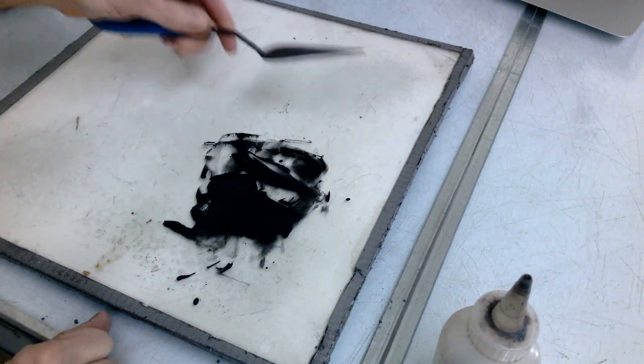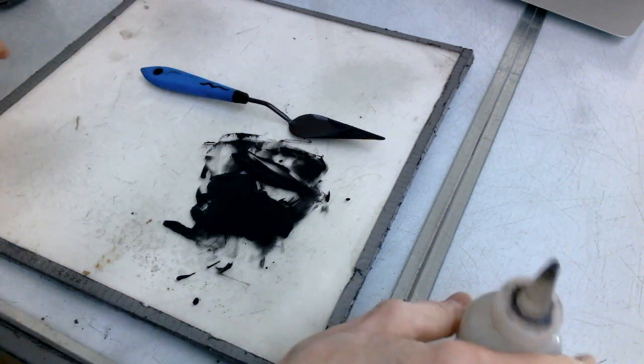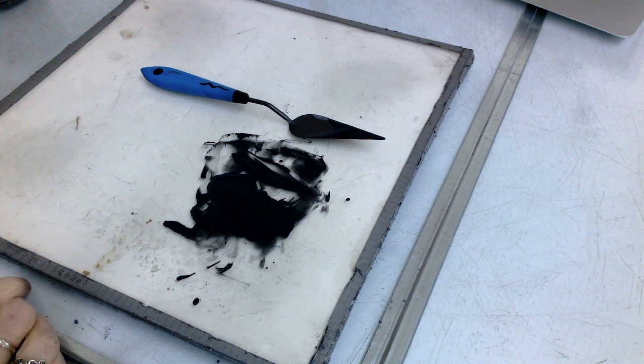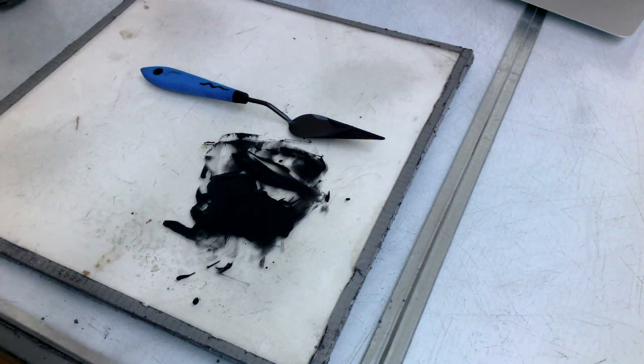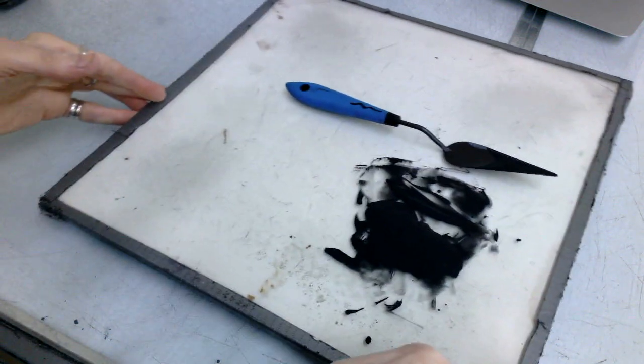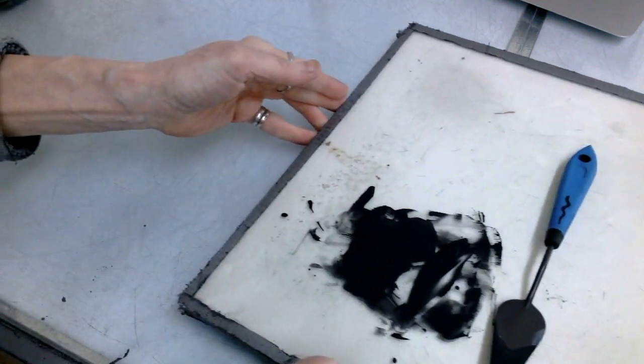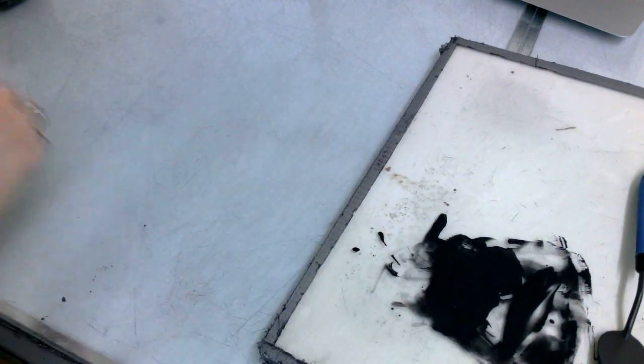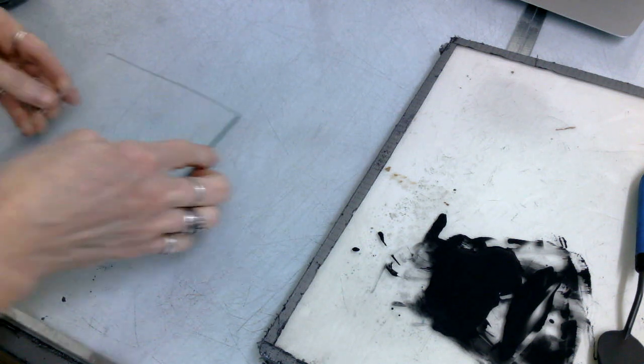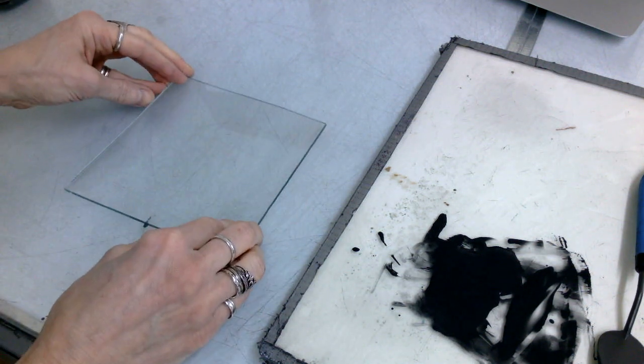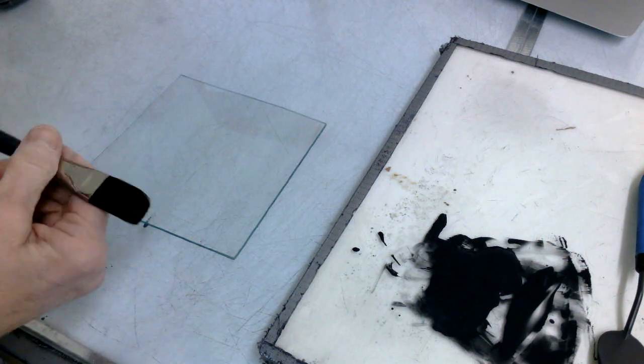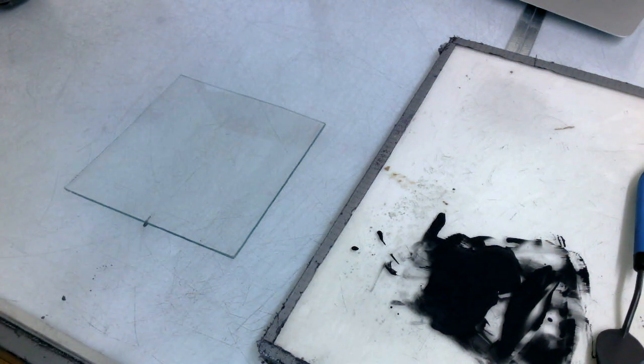So here's another thing about glass paint. There's no such thing as painting thick. I have never seen an impasto made of glass paint. Why is that? Because the paint needs to fuse to the surface of the glass when it's in the kiln. And too thick, the outside layer would be basically trying to fuse to itself. It wouldn't be near the surface of the glass. So typically, glass matting is on the thin side.